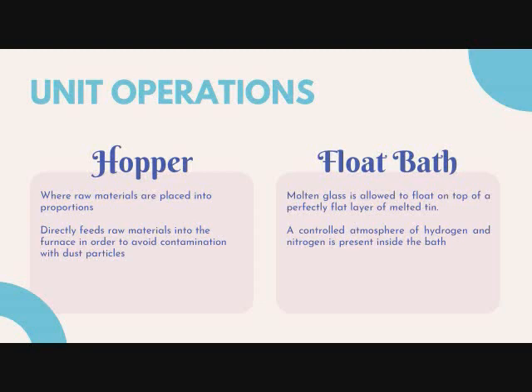Next, the float bath. The float bath is where the liquid glass produced from the furnace is transferred onto. The temperature of this molten glass is about 1100 degrees Celsius, and it is allowed to float on top of a perfectly flat layer of melted tin. The molten glass is less dense than tin, which allows it to float. Tin and molten glass do not mix, and tin also has a higher boiling point than that of molten glass. The molten glass leaves the tin bath at around 600 degrees Celsius. And in order to prevent the tin from oxidizing, a controlled atmosphere of hydrogen and nitrogen is present inside the bath. The next unit operation is annealing.